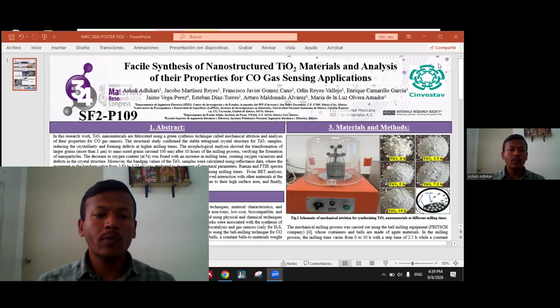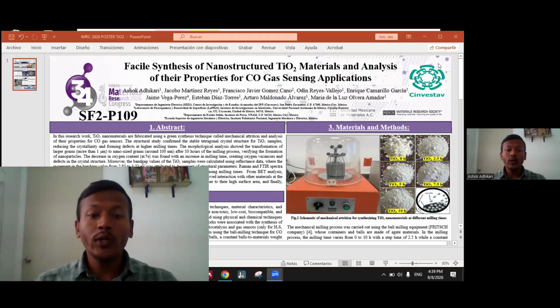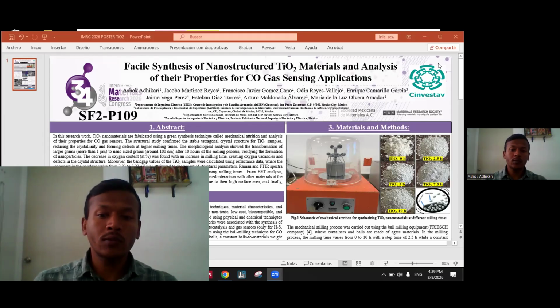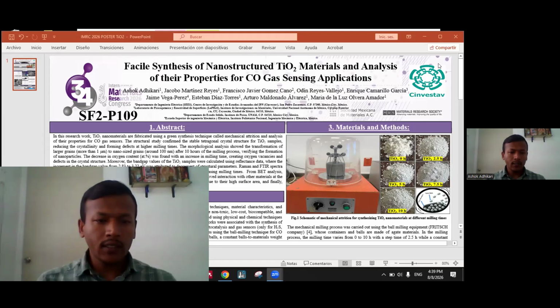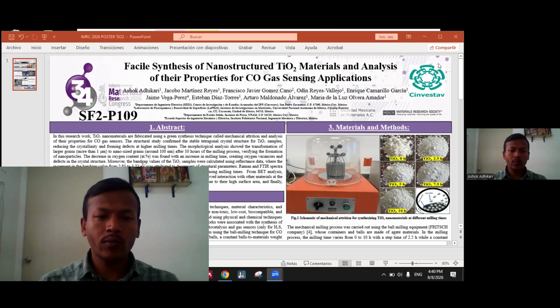Verifying the formation of the nanoparticles, a decrease in oxygen content of 20% was found with an increase in milling time, creating oxygen vacancy and defects in the crystal structure. Moreover, the band gap values of the TiO2 samples were calculated using reflectance data, where the increment in the band gap value from 2.83 to 3.22 electron volt was attributed to decrement of structural parameters. Raman and FTIR spectra of TiO2 samples revealed an increase in structural defects and lattice disorder with increasing milling times.